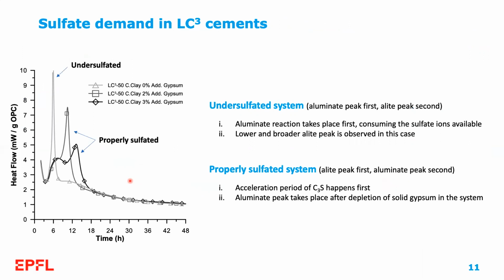Why do we need to study sulfate demand in LC3? Well, this is important because in some cases we can end up in a situation like the lightest gray curve here, which is what we call an undersulfated system. This is when the aluminate peak occurs first, followed by the second alite peak. In this case, the alite peak, which follows, appears depressed, and we have a lower degree of hydration of alite at 24 hours, compromising the early age strength of our blended cement.